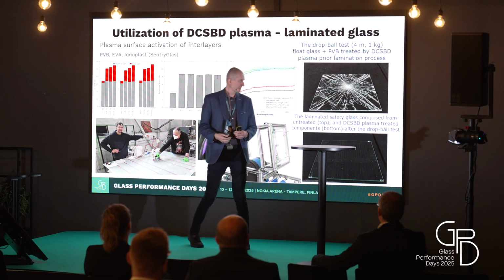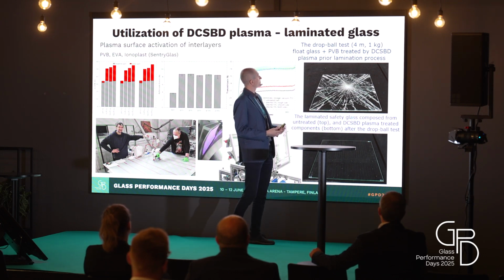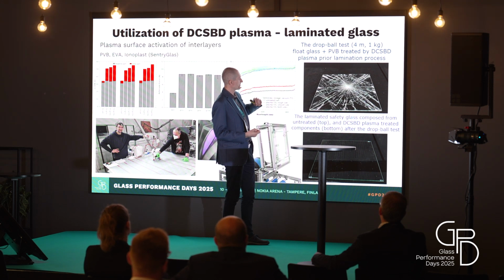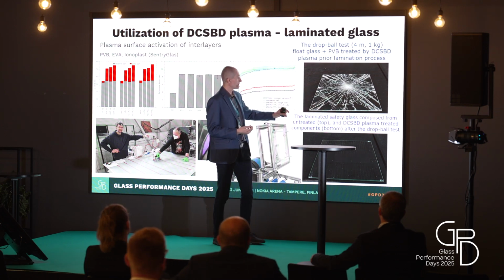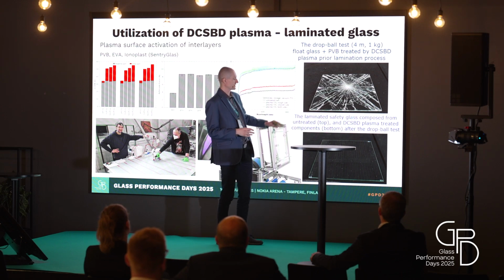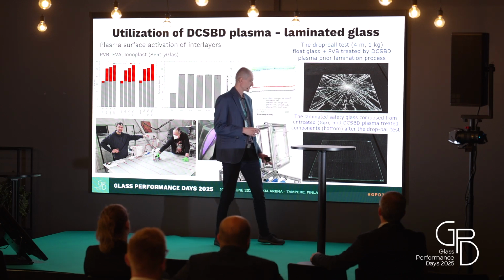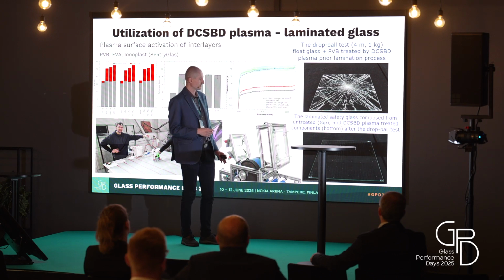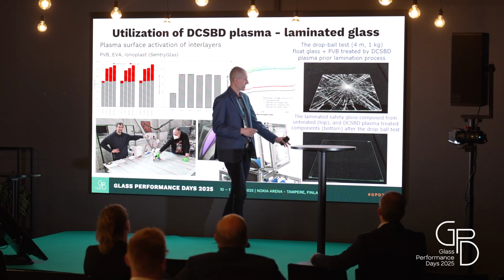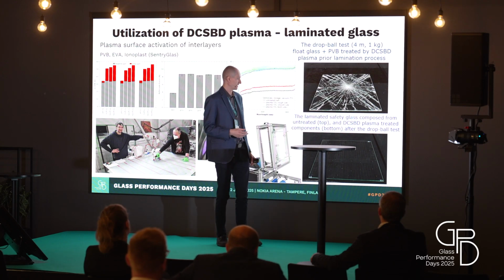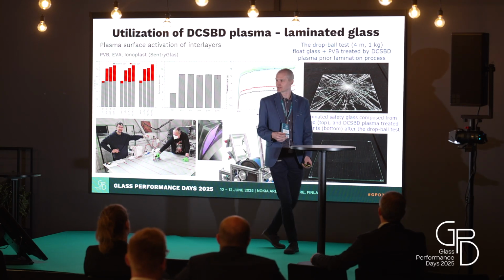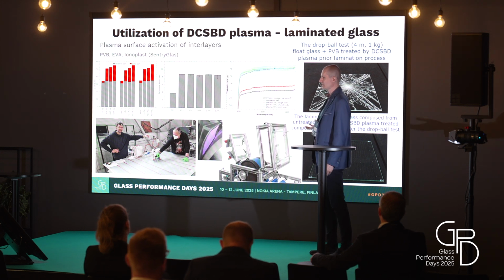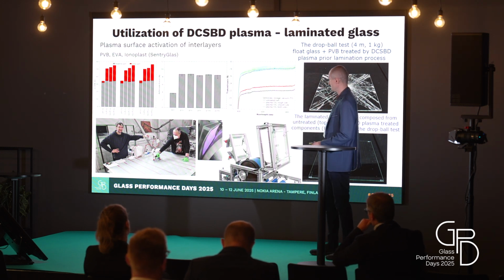And here I have the result of the drop ball test on the samples where both glass and interlayer were treated by our plasma system. This is the reference sample without any application of plasma, just standard cleaning, and this is the result when the same test was applied on the sample with plasma application. So, a very big difference. Again, this is done by the interface improvement between the interlayer and the glass.